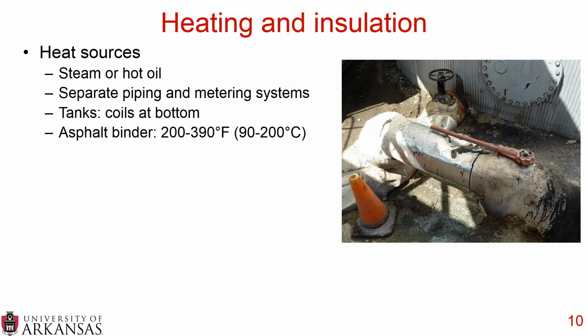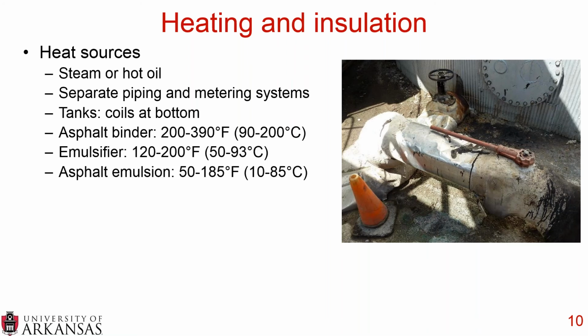Tanks generally have coils at the bottom, and that's another reason why you want to be able to stir the asphalt emulsion, or you can recirculate the asphalt binder through pipes. Those coils at the bottom are the heat source, so you don't want just the bottom getting heated. You want it to be a homogeneous temperature throughout the entire tank. Now, asphalt binder, depending on the grade and whether or not it's polymer modified, as CJ was talking about, can be anywhere from 200 to 390 degrees Fahrenheit. The emulsifier is anywhere from 120 to 200 degrees Fahrenheit, and emulsion is anywhere from 50 to 185 degrees Fahrenheit.